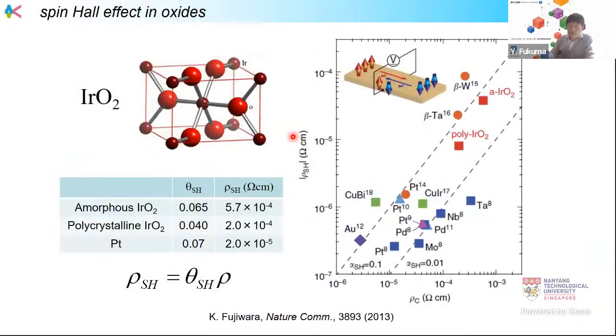Not only for metal, we can also see the spin Hall effect in oxide materials. For example, here is iridium oxide. In the case of iridium oxide, compared to platinum, the spin Hall effect is not too high. But we can see here that the resistivity is increasing.